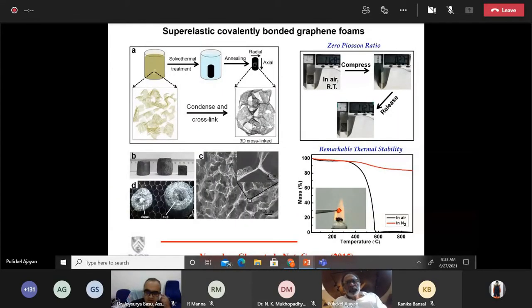So ultimately, you can think of building these type of porous 3D structures from these building blocks like carbon nanotubes or graphene. This particular image shows the 3D constructs from graphene, and they show some remarkable properties, especially we were looking at superelasticity. So structures made from these graphene-like materials in 3D show superelastic behavior or elastic behavior at very, very low temperature, all the way from cryogenic temperatures to a very high temperature, about 1,000 degrees or so. So by combining the right kind of nanomaterials and the right kind of engineering, we can build structures that are really superior in properties compared to most of the existing materials today.